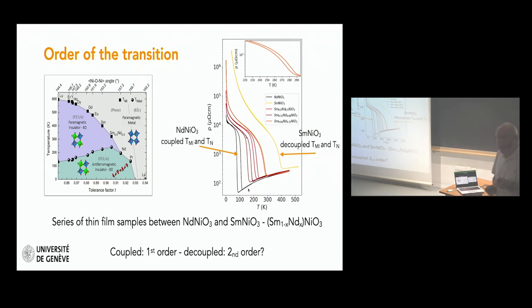But now if you measure samarium nickelate, neodymium nickelate is here, samarium nickelate is here. When you measure samarium nickelate, you see no hysteresis in the measurement. And it has been proposed that the reason is that when the two transitions, metal to insulator and magnetic transition, are coupled, like for neodymium nickelate, the transition is first order, but when they're decoupled, the transition is second order. So we decided to study this, and what we did, we grew some solid solution films between samarium nickelate and neodymium nickelate. So we grew materials like the one you see here.